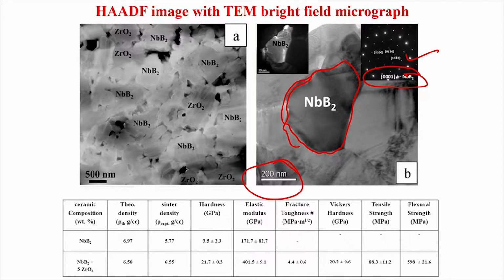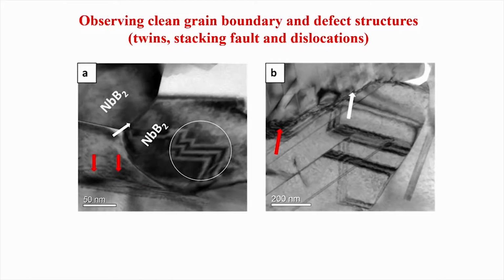Now, in terms of the different properties, for example, sintered density, niobium boride has a sintered density of 6.55, while the theoretical density is 6.58, so it is close to the sintered density. Hardness is 21.7 gigapascal, which is very high. Elastic modulus is 401.5 plus or minus 9.1 gigapascal. Fracture toughness is 4.4 MPa square root meter, and tensile strength is 88.3 megapascal, and flexural strength is around 600 megapascal, which is a combination of properties that is not bad.